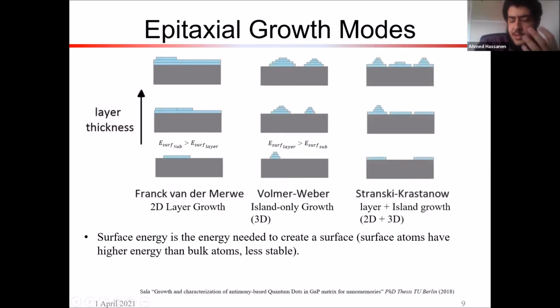And the main mode used for quantum dot formation is the Stranski-Krastanov mode. And so depending also on the energy considerations, you start to get this 2D wetting layer when we're growing. And then you start to get these islands growing on top of it. And so it's a mix, a hybrid mode maybe. And these islands form the quantum dots that we want. Surface energy is just basically the energy needed to create a surface.